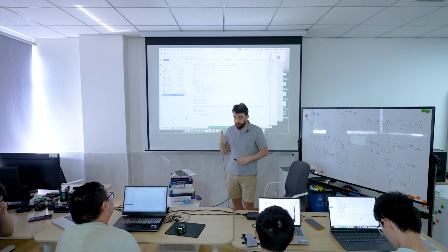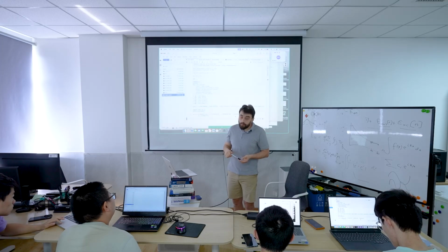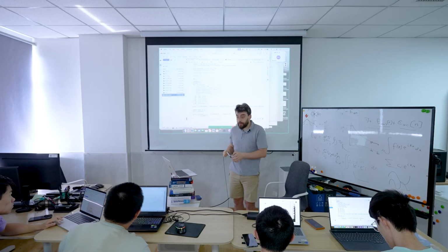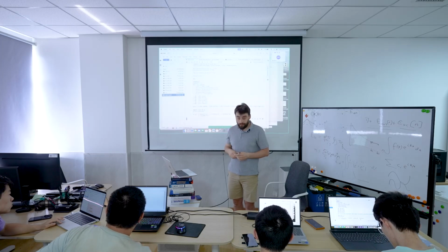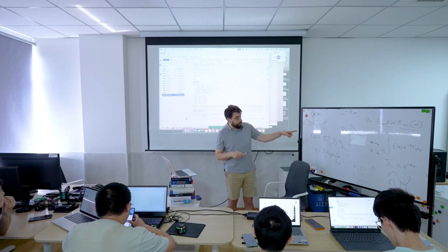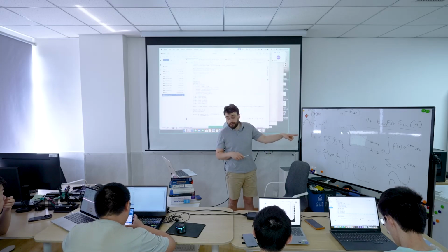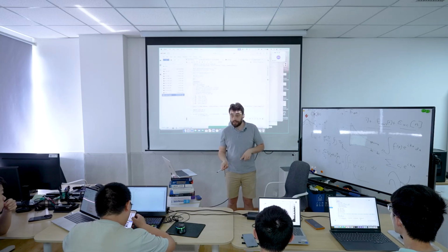So that's my rule of thumb. That's what I would normally stop at, 10 to the minus 2. But if you have a particularly accurate experiment, be very careful. Because just because your plane wave basis set is converged at 10 to the minus 2 doesn't mean that your calculation is predictive to 10 to the minus 2.